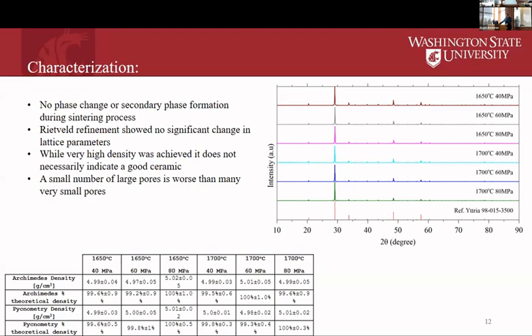What we found is that just a simple density number is not enough to really tell us what we need to know. It's not actually the density, but more a matter of the number of pores and the size of those pores. You could have a significantly lower density with very small pores and be fine. What you can't have is a very high density with a few very large pores, like we have.